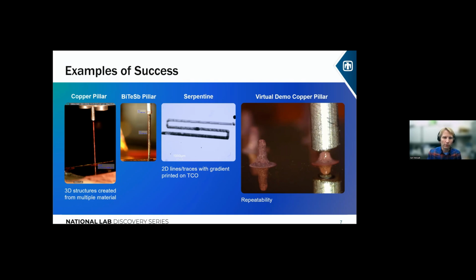And then our rightmost photo is a copper pillar being printed in real time. So the silvery metallic, that's the print nozzle, and that is printing a copper pillar about 1 millimeter tall and 400 microns in diameter. And what you're seeing here, at the very start of the print, the meniscus was contacting the substrate below, and then as that structure grows, as the copper deposits, the structure grows up and the nozzle moves up. There's a feedback loop that helps with the automation of controlling the growth or the movement of the print head. And as it grows up, the meniscus grows or moves along that printed surface.